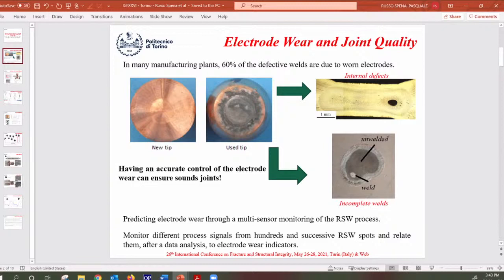However, a direct measure of the weld nugget size is not possible because it remains between the two sheets, and therefore the joint quality is normally assessed through destructive tests. This has fostered research toward many indirect measurement methods for evaluating joint quality, many exploiting process signal curves and non-destructive test analysis. As you can see from this picture, electrode wear is generally the most important cause of defective joints, inducing voids inside the weld nugget or, in some cases, incomplete welds. That's why predicting electrode wear through multi-sensor monitoring of resistance spot welding can be an important aim for properly evaluating the quality of spot welds during the process itself.